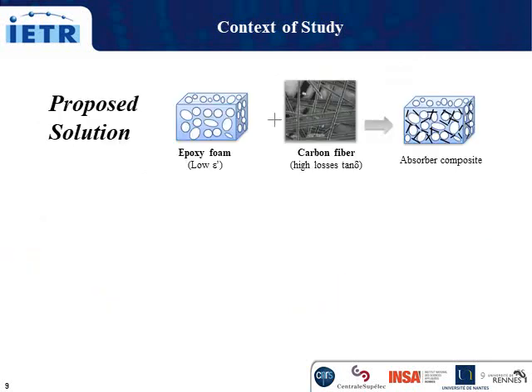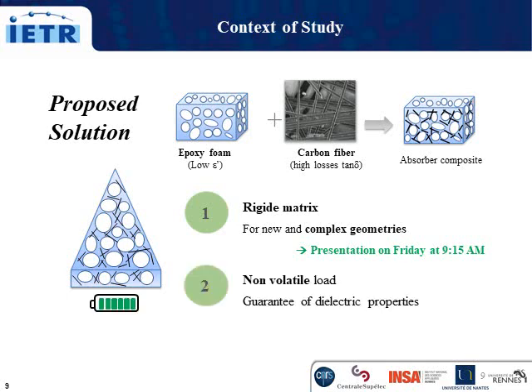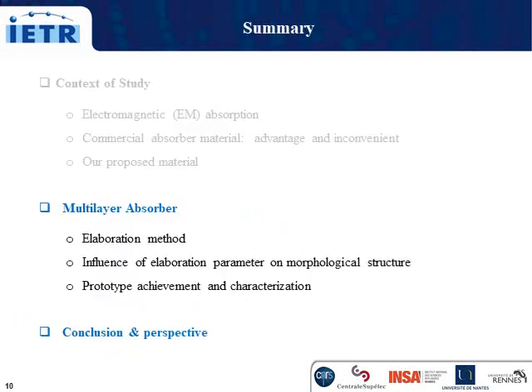In order to overcome the limitations of commercial materials, we propose to study new absorbing materials based on epoxy foam loaded with long carbon fiber. The rigid foam permits the achievement of new and complex geometry for the optimization of absorption performance. On the other hand, carbon fibers are non-volatile loads, and their use guarantees good performance over time. But this proposed material presents a high density of about 0.14 gram per centimeter cube, compared to the commercial absorber with a density of 0.07 gram per centimeter cube. So the objective of this work is to reduce the density of this composite, reduce the thickness of this absorber, and use a low amount of load, keeping the same absorption performance.